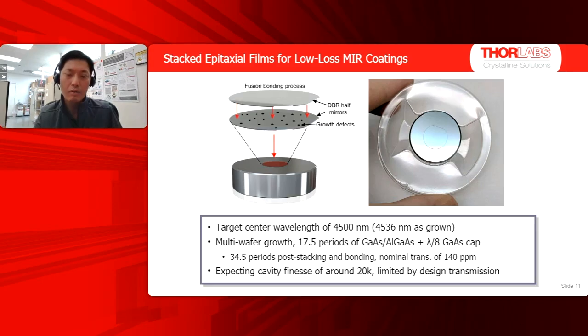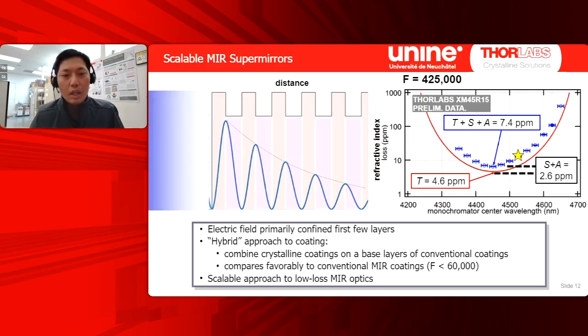But the downside is we have this 2-step bonding process, which actually made scaling these mirrors to production a little difficult. So then the next thing we recognized was that actually it's only the first few layers of the interference coating that sees the majority of the electric field. What I've shown here is the index as a function of distance into the multi-layer. You can see there's high index, low index, high index, etc. And it's exactly a quarter wave stack. Coming in from the left is some incident light, and then the blue squiggle is the expected field inside the multi-layer. And you can see it decays quite rapidly.